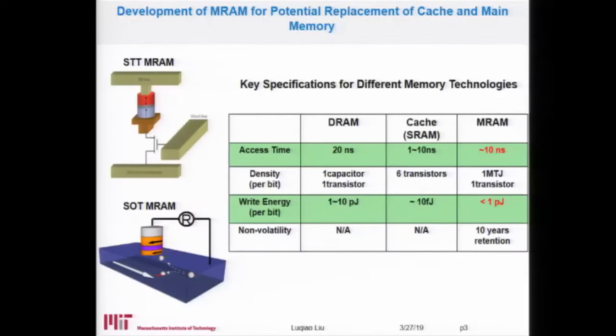But nowadays, with the development of some emergent memory devices, for example, magnetic memory, MRAM, magnetic random access memory, it makes it possible to simplify the memory architecture as shown here. For MRAM, the accessing time is on the order of 10 nanoseconds, and in some extreme cases, you can push it even below 10 nanoseconds. So it's very close to the speed performance of the CPU. At the same time, it also has a very small footprint. For example, it is a one MTJ, one transistor design, one cell, one transistor design. So that can make the memory density quite high, which means you can potentially make it a main memory.